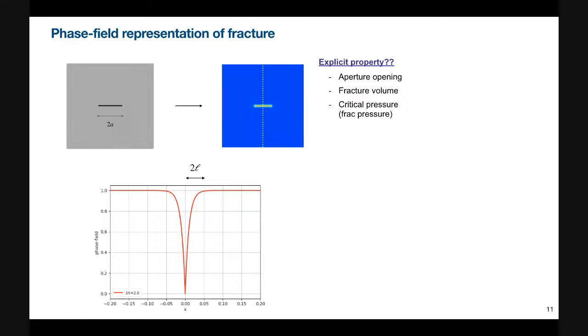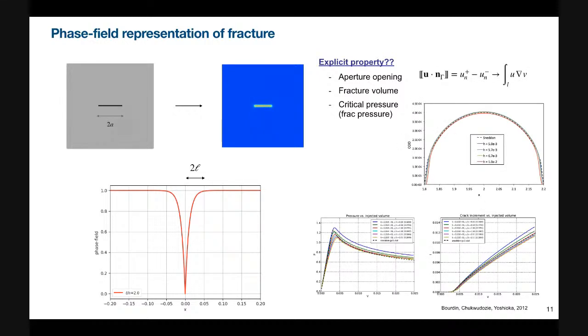So the question now is, can we still recover explicit properties? With a diffused crack, how can we define such explicit properties, like fracture aperture or volume or critical pressure or frac pressure? The fracture aperture is a displacement jump across the crack surface. And since the crack surface is diffused, we recover this by taking this integral.